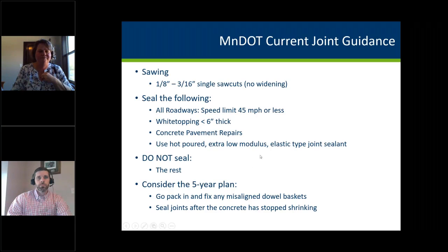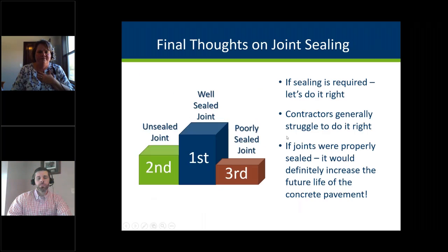Oh, there they are. We use single saw cuts on all of our pavements, and we use hot pour, low modulus hot pour. We know we're just filling the joints, we're not sealing them, but we especially are interested in the lower volume roadways because the traffic just can't pull that debris out. So we want to do whatever we can to keep the incompressibles out.